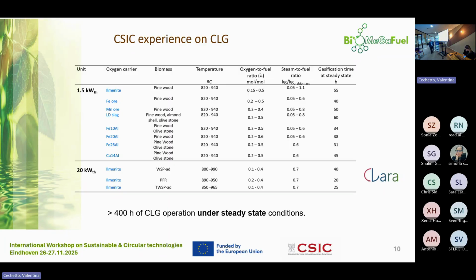And also in the 20 kilowatt unit, in this case with the oxygen carrier selected being ilmenite, we got more than 400 hours of operation under steady state conditions.